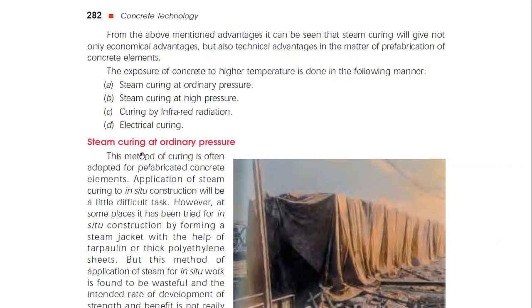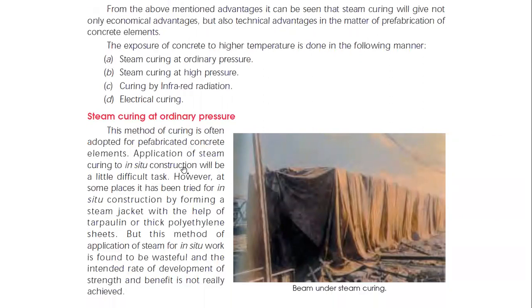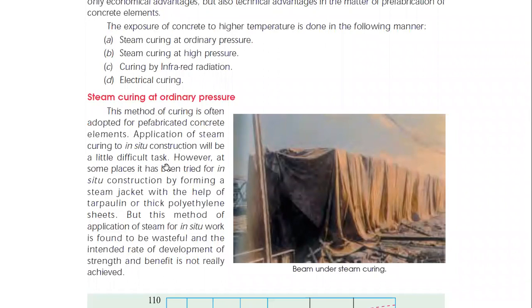So first one is steam curing at ordinary pressure. So basically it is the method of curing often adopted for prefabricated concrete elements, and application of steam curing to cast in situ construction will be a little difficult task. However, at some places it has been tried for in situ construction by forming a steam jacket with the help of tarpaulin or thick polyethylene sheets. But this method of application of steam for in situ work is found to be wasteful, and the intended rate of development of strength and benefit is not really achieved.